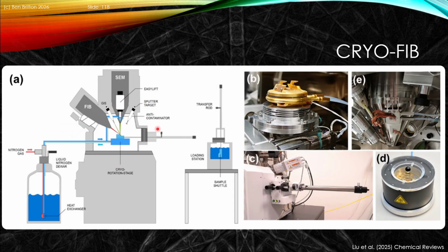Now effectively we have a cryogenic transfer system that enables us to have the cooling systems, anti-contaminators, cooling of a variety of bits and pieces around the column, but we can also have a cryo rotation stage on a long arm that enables us to take the sample in and out and bring it via a loading system. And so this is the overall system where you can now have an arm that's attached to the side of this, and this can be particularly important for things like battery materials, where you might not want to have the electrolyte or the such doing various things.